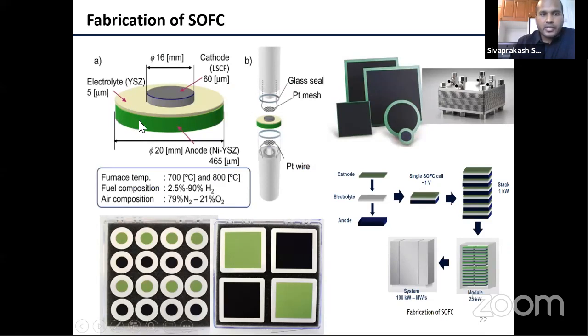Fuel cells are conventionally fabricated by pressing or tape casting methods. First, the green color is the anode material, nickel and zirconia mixed as a composite, tape casted. The second layer, this yellow layer, is the electrolyte material, yttria stabilized zirconia, which is tape casted and deposited. The third layer is the cathode, deposited by screen printing or spray coating methods, followed by sintering at 1500 degrees Celsius.